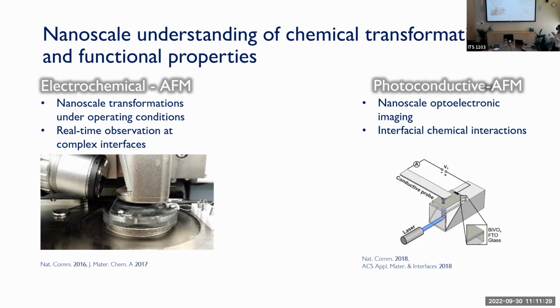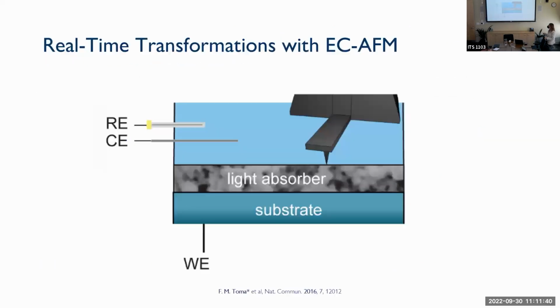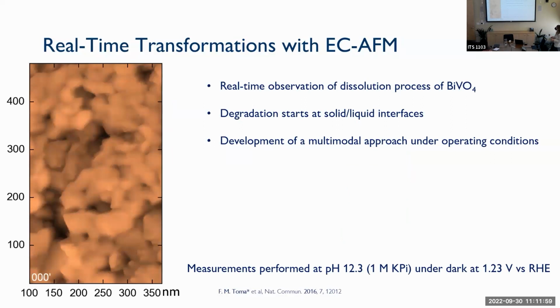And you can also use this technique to look at functionality. If you shine light on the sample, you can also collect current from the sample. And you can get maps of photocurrent on the sample. So this is how the system works. As I told you, this is the tip of the atomic force microscope. It's on a cantilever, and you scan it on top of a sample, a light absorber in this case, which is also your working electrode in the electrochemical cell. And then you have a counter electrode and a reference electrode. And then you can collect videos of your sample, and you can understand how the material is degraded.